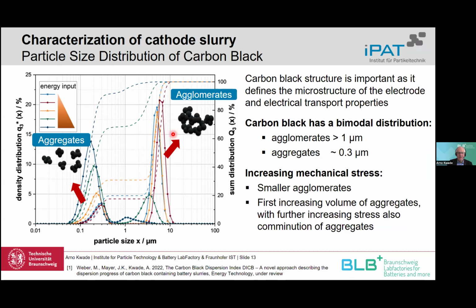So at the beginning, you have a lot of agglomerates of the carbon black, and with increasing dispersing, these agglomerates are dispersed to aggregates, very close, strong aggregates. So they are shifted in this direction. For really high dispersing, almost no agglomerates exist anymore, and we have only aggregates on the left side. But it's not the goal. I will show it later, to have only aggregates, because we need some short range and also long range conductivity. So there should be a good mixture of aggregates and agglomerates in our suspension for the later performance of the cell.